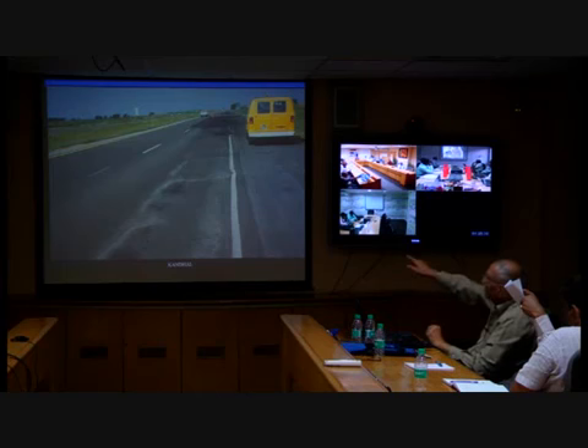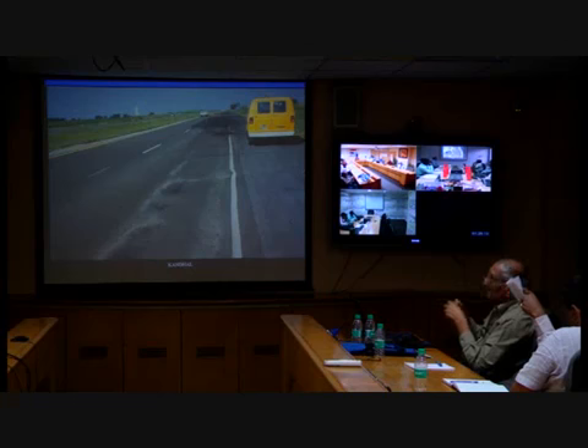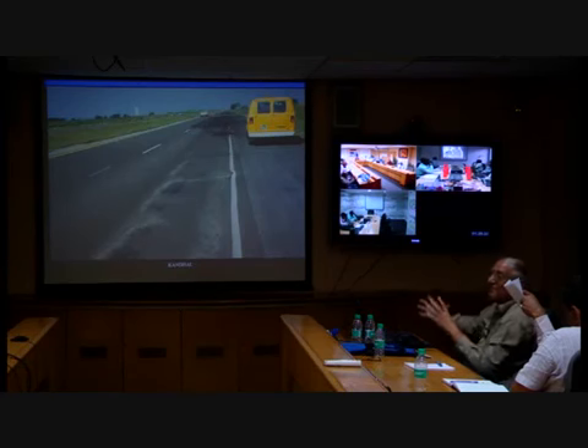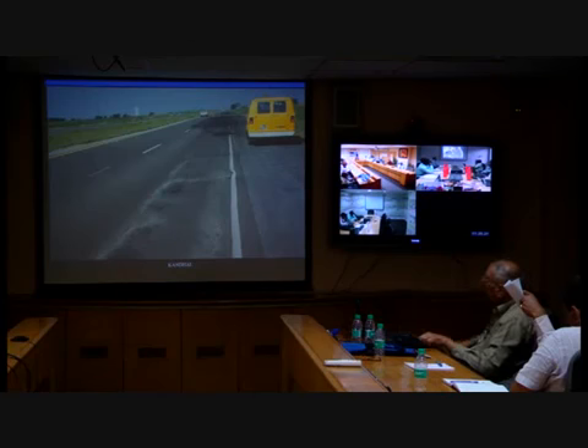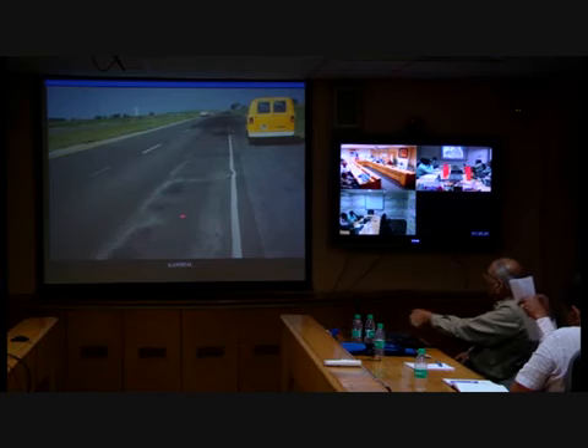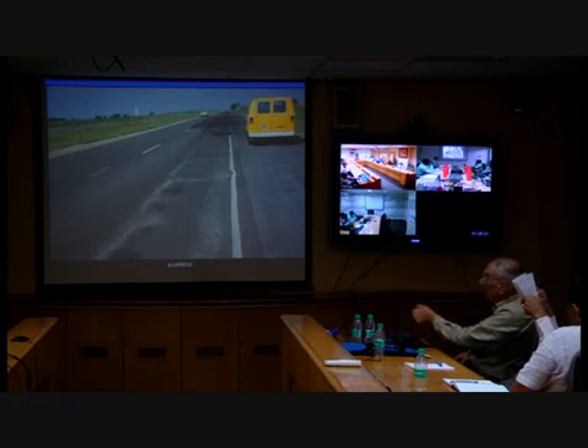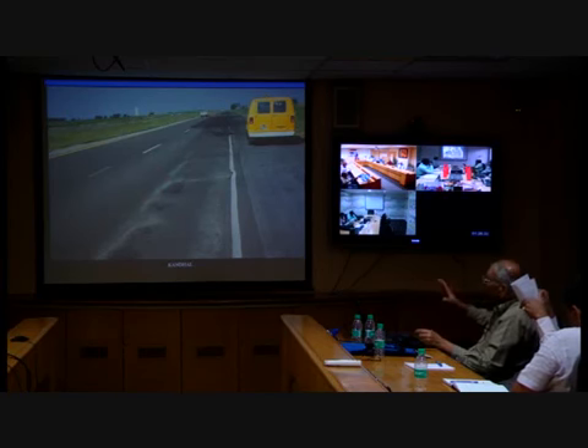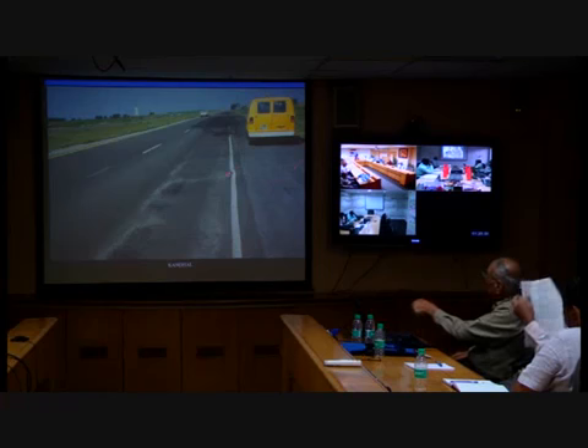So we see white stains, and then eventually after a few months, the bitumen which was stripped off will start to migrate towards the BC surface. It always migrates up, because of some moisture, vapor pressure or whatever. So then we see some black bleeding spots. You see this white surface here, and the black surface is the bleeding. And then after it starts bleeding, you start to see potholes.